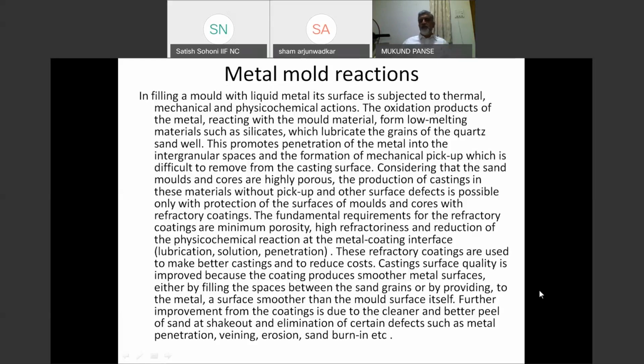When the metal is poured, with the hydrostatic pressure, or because of the high fluidity at these temperatures, it goes into the pores between the two sand grains. The sand grain between the metal gets fused because at that temperature it doesn't retain its thermal characteristics, and you get a fused layer of sand on the surface.